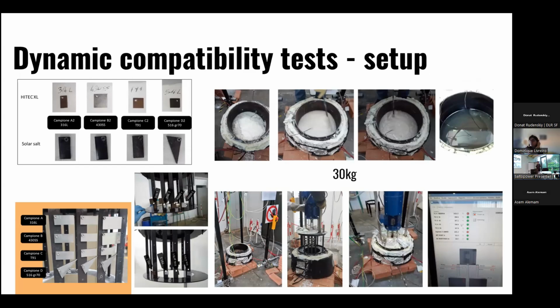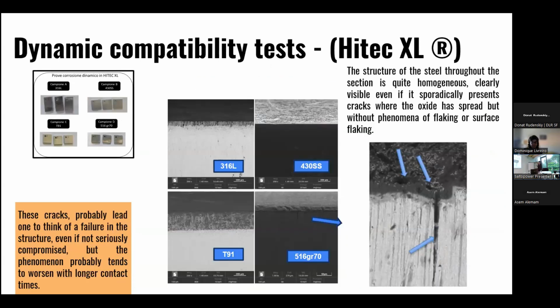This facility has a huge stirrer that simulates the flow of a real plant. We decided to test the same steels of our lab-scale tests with HITEC XL and with solar salt at more or less the same temperatures. And even in this case, it was very evident with HITEC XL.